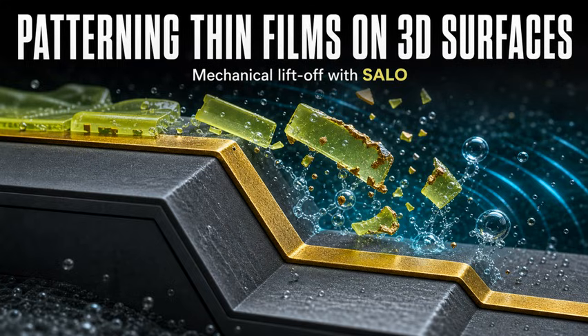Wait, but if I'm printing a standard IP-Dip scaffold directly onto a polymer substrate, applying the laser is just going to cross-link them together? I mean, they'd permanently fuse, right? You couldn't snap that off cleanly. They absolutely would fuse, which is why the paper outlines a really great workaround. For polymer substrates, you first deposit a 10 nanometer sputtered silicon dioxide layer. Oh, so like a barrier layer. Exactly. It acts as a diffusion barrier to stop the IP-Dip from covalently cross-linking to the base, ensuring the fracture happens cleanly right at the interface.